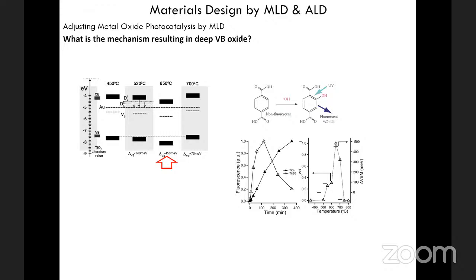And this was something that we were quite convinced that we have to explain also by looking at the fluorescence spectroscopy of terephthalic acid being decomposed by TiO2, which is conventional TiO2 here, and titanium ethylene glycol at 650 C. So what you can see here is expected that for TiO2, the more you shine UV light, you form more of the OH adduct of terephthalic acid, which fluoresce, and fluorescence increase until you get some steady state level, and that's it, because TiO2 would not decompose this molecule.